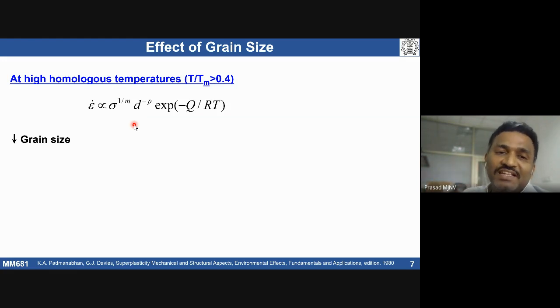That way you can deform material very easily if the material has a fine grain size. The other thing, if you have finer and finer grain size, the effective diffusion path, the length scale of diffusion, is going to be smaller. You can have improved diffusivity because we have a large grain boundary area. The grain boundary area is going to increase with refining the grain size, so that can lead to increased diffusivities in the materials. The flow can happen very easily if there is improved diffusivity, so atomic movement can happen very nicely. So they can have improved deformation, improved elongations. These are the beneficial things we see.